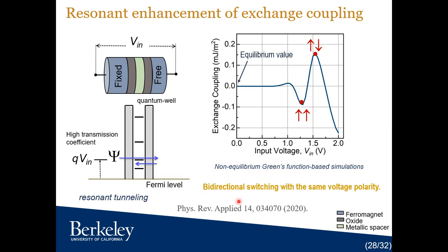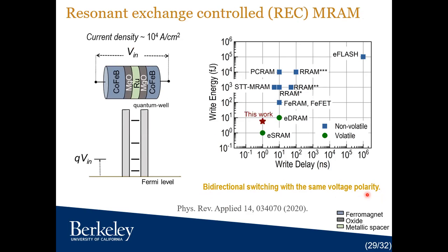And bidirectional switching will be achieved for the same voltage polarity but different amplitude. So this is quite different from what people know. Based on this particular materials combination, we calculated that the current density at switching can be very low. So we assume cobalt iron boron as the magnet, magnesium oxide as the barrier, and ruthenium as the thin metallic spacer. And the current density can be 10 to the power 4 amp per centimeter square.